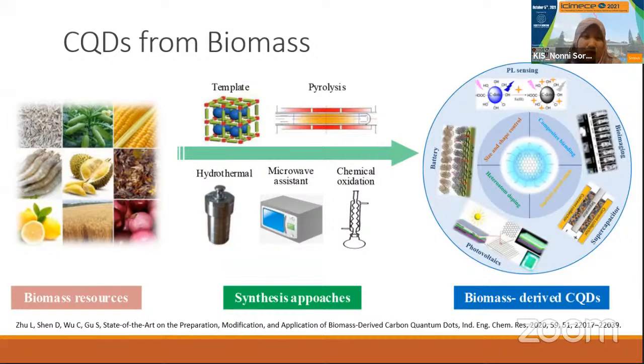So what kind of synthesis methods can we use? First of all, we can use the hydrothermal method. We apply a certain high temperature to a solution containing a carbon precursor, and at the end of the reaction, we get the carbon quantum dots. The other process is microwave-assisted synthesis. Pyrolysis synthesis can also be used. Not only the ones that I show in this slide, there are many other synthesis approaches to convert biomass into carbon quantum dots, even by using laser.